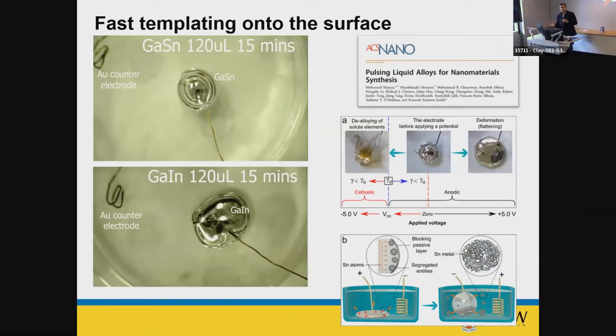This time, we can start from the core. How do we do this? We dissolve the secondary metal in the core, right? And then you apply the voltage on the surface. You disturb the equilibrium of the surface. You can bring the secondary material from the core to the surface and spit them out. And that's very interesting. Still, we are studying it.